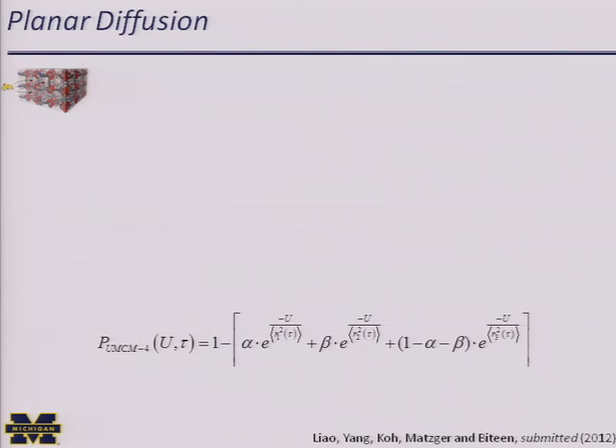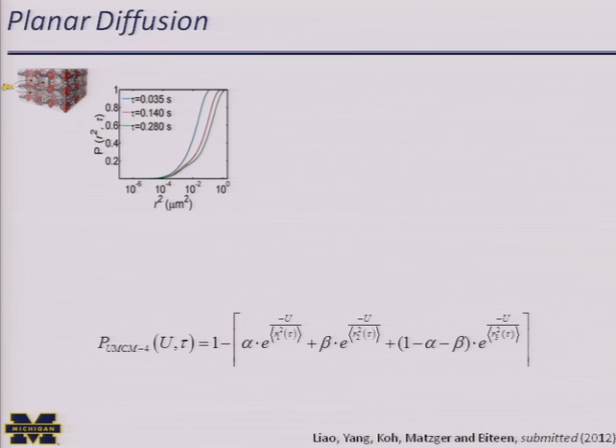And then we can do the same thing for the 2D case. Here, our function looks a bit different. But again, we have three components. Fitting an immobile component in this case did not work. So we fit three different components. And what we assumed here was that we'd have three MSDs, a fast diffusion coefficient, a medium one, and a slow one, and that the slow diffusion would be essentially immobile molecules, but we weren't sure exactly what to expect. So we fit many of these functions again, and now because this model is different, there's some interesting features like the shoulder.